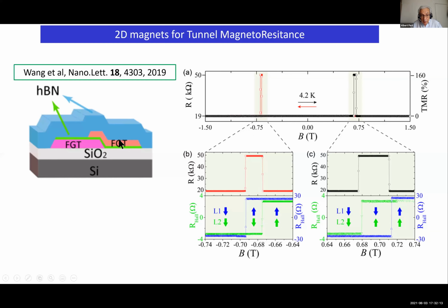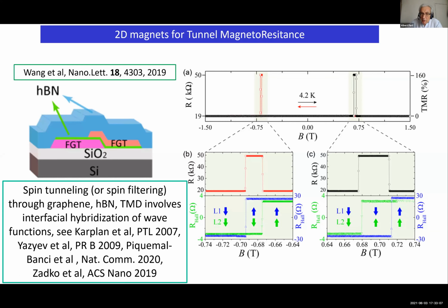That is, when you sweep the field, the reversal of the magnetization as a function of the field is not at the same field for the bottom and top layer. And so you can see in the range between the reversal of one of the electrodes and the reversal of the other, there is an increase of the magnetoresistance, the TMR effect, as you can see here, corresponding to the crossover between parallel magnetization, anti-parallel magnetization of the two layers of FGT, and again, at higher field, parallel magnetization. So it's not really surprising. If one looks at the difference between the TMR with 2D materials and with 3D materials, it is that in 3D materials, finally, the models are relatively simple. In first approximation, one can say that the TMR depends on the spin polarization of the density of states in the electrodes.